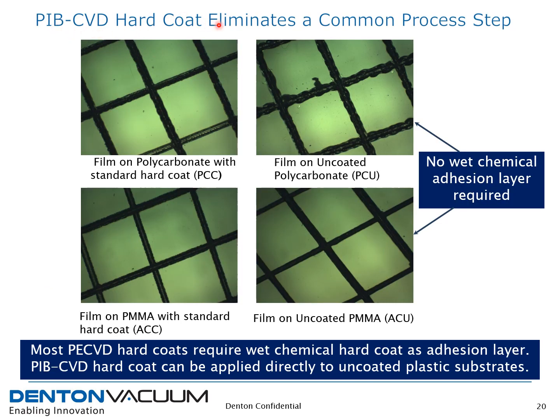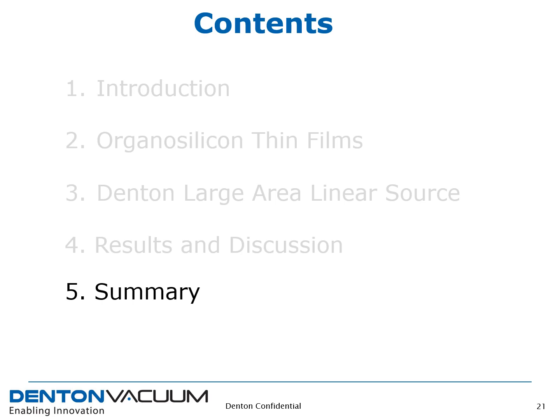PIB-CVD hardcoats can eliminate a common process step in PE-CVD hardcoats. This is because most PE-CVD hardcoats require an adhesion layer, which is commonly applied by wet chemical methods. However, as shown here from the cross-hatch tape test, PIB-CVD hardcoats have good adhesion both to the substrates with the standard wet chemical hardcoat as well as to the uncoated substrates. This is possible with our PIB-CVD process only because of the wide range tunability of ion energies. So a multi-layer structure can be deposited directly on uncoated plastic substrates to transition the hardness of the plastic surface from polymer-like to glass-like.